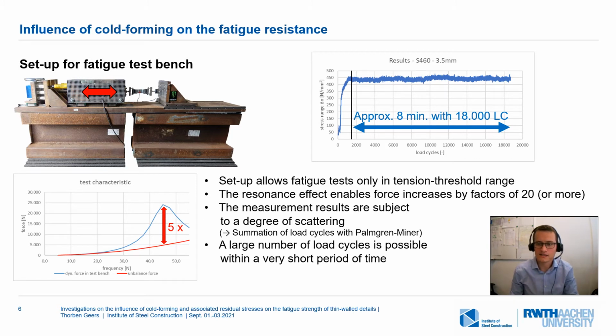On the right hand side you can see the extension of an experiment and a relatively high scattering of the stress range. This is the disadvantage of resonance. The control does not allow a constant load, which is why a summation of load cycles is necessary with the help of the linear damage accumulation according to Palmgren-Miner.